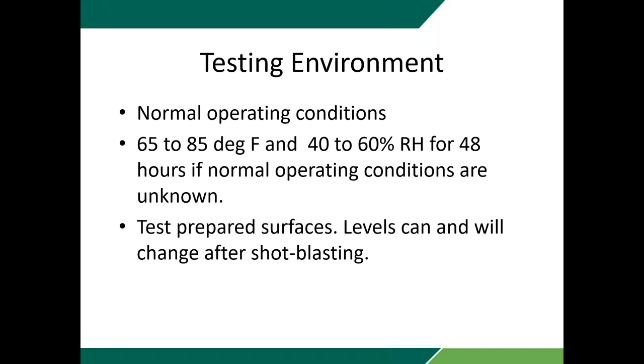Anytime we're running these tests, it's very important to consider the environment that we're testing in, because that can change things. That's particularly with the moisture vapor drive tests. So we want to have the floor or the room under normal operating conditions, and have it that way for a given period of time before we actually run the test. Don't turn the heat up to 70 degrees tonight and then come back and run the test tomorrow morning. We want that slab to acclimate to those conditions in the room.